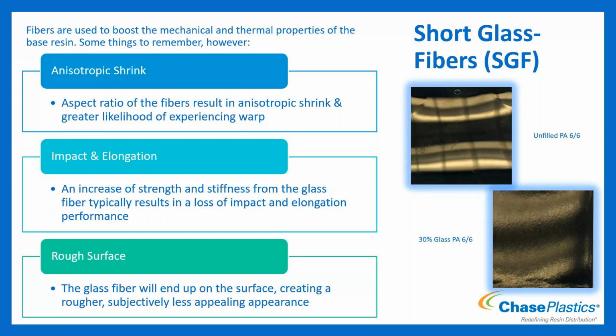Impact and elongation - as I mentioned, you see an increase in your stiffness and strength. You're generally going to see a decrease in your impact and elongation. The other thing to keep in mind that I've not mentioned yet is the rough surface. So even if you bury the glass pretty well, you're still going to rough up the surface just a little bit, and in most cases you actually rough it up quite a bit.